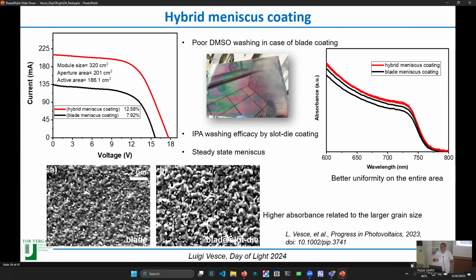So the substrate is too big, and we cannot control this by blade. And so we use the slot-die coater for the anti-solvent step, and we can improve the efficiency to 12.6%. And also in the absorbance spectra, you can see the better uniformity.